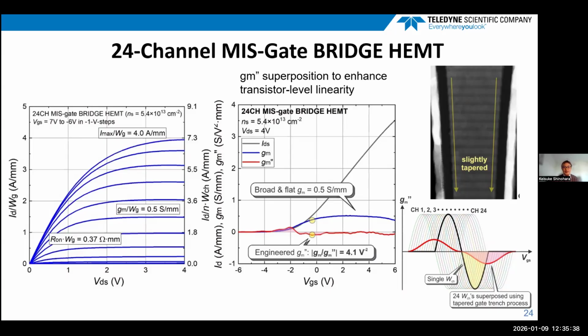On the right bottom, I showed the mathematically calculated gm curves with multiple channel widths, which is shown in the red curve, as compared to the single width case. By using this superposition technique, we can reduce the gm double prime, which is important for linearity enhancement at low power level. As a result, this transistor shows a very small gm double prime curve, as well as a flat gm at high current density.